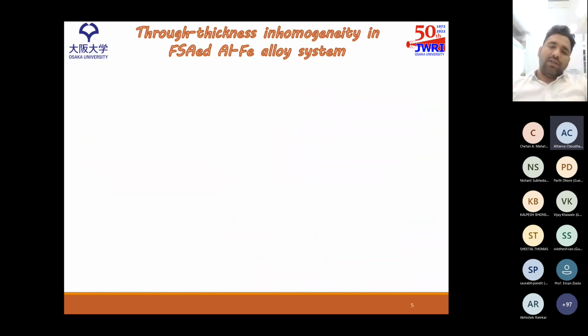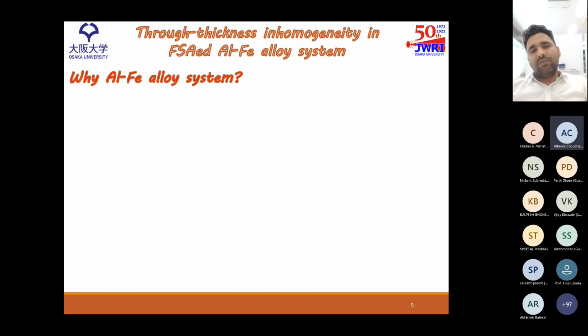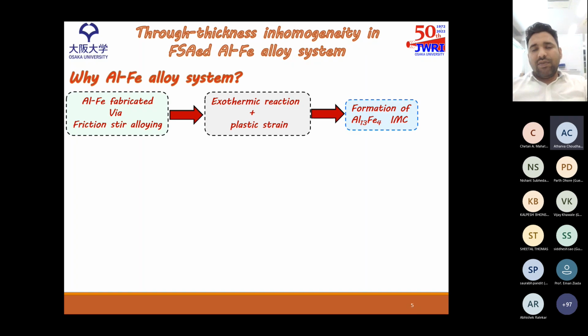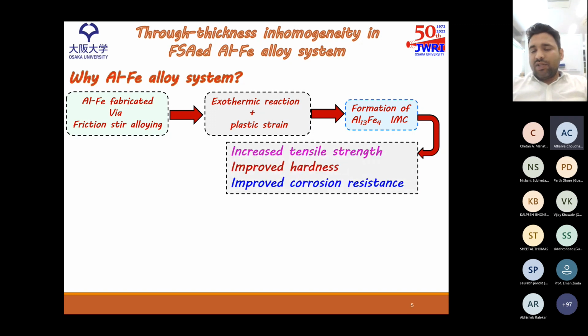Now coming to the first project that I'm working on here, that is the through thickness inhomogeneity in the friction stir alloyed Al-Fe alloy system. Now after the title, the question arises: why the Al-Fe alloy system? Because in the Al-Fe alloy system, when it is fabricated by friction stir alloying, there is a generation of plastic strain and exothermic reactions. These lead to the formation of Al13Fe4 intermetallic layers. This intermetallic layer, when reinforced in the aluminum, increases the tensile strength, improves the hardness as well as the corrosion resistance.